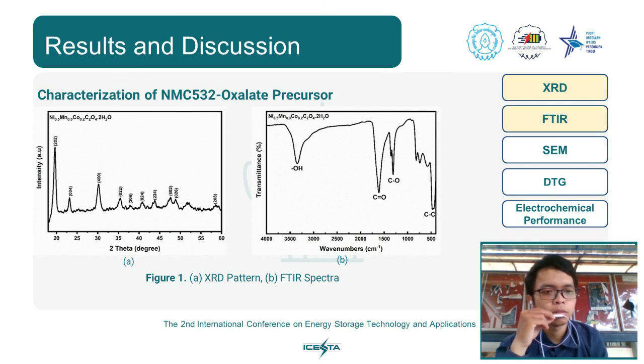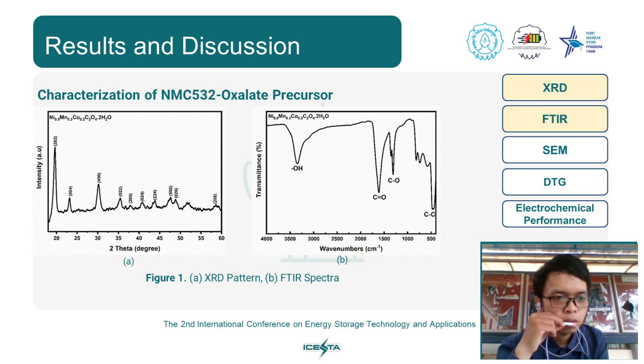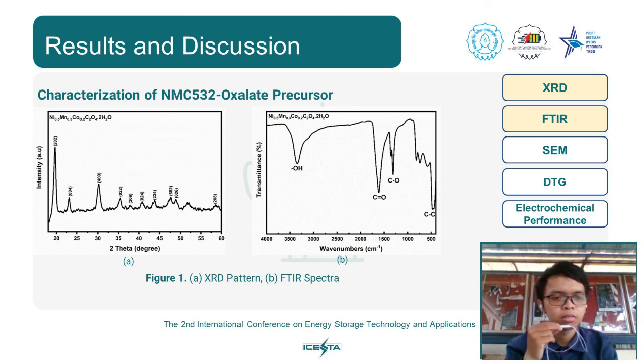Here is the characterization of the NMC 5:3:2 oxalate precursor using XRD and FTIR tests. From the XRD test results, a sharp peak indicates the sample has a good crystal structure. However, on the test result curve, there are still small peaks that indicate the presence of impurities, such as oxalate groups, which cause the precursor to be amorphous. From the FTIR test, there are some functional groups of organic compounds that indicate the presence of oxalate groups.